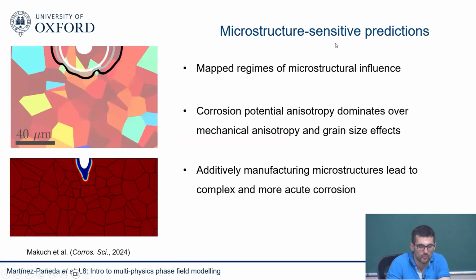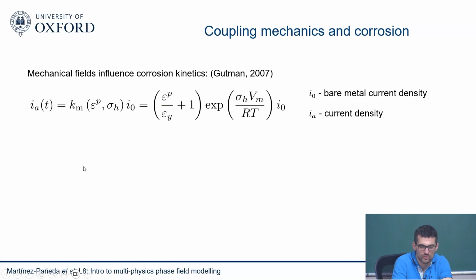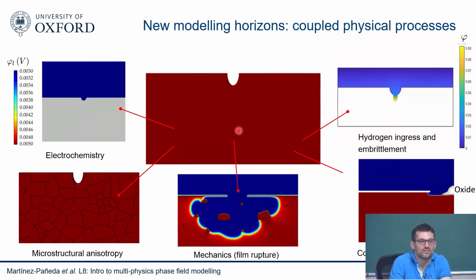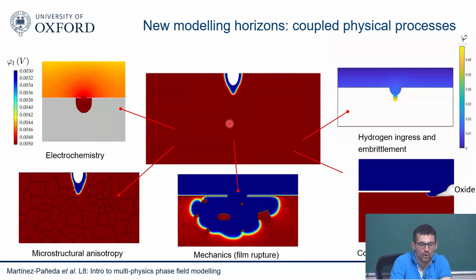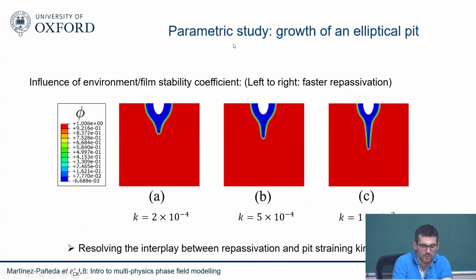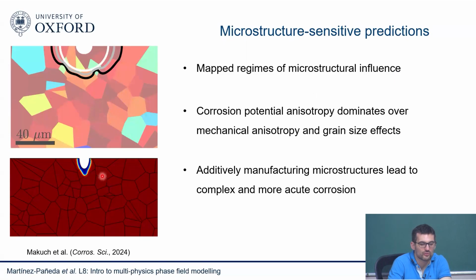And then when you do that, you can see that you were looking at this case, so this problem here is a pit growing into something that is loaded uniaxially, so it's very similar to this one here. You can see that in the case of isotropic, this defect just grows in a symmetric way, but of course this breaks down the moment you're doing some sort of microstructural anisotropy. So you capture the effect of microstructural anisotropy. And this for us was important. So of course you need to do multiple simulations, this is the evolution of the pit as well, with different sort of RVEs, so to say. They're not really RVEs, but these representative domains where you can play around. You can do different grain boundaries or different grain sizes and so on and so forth.